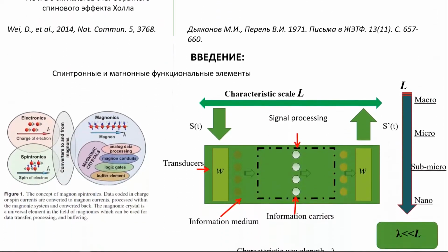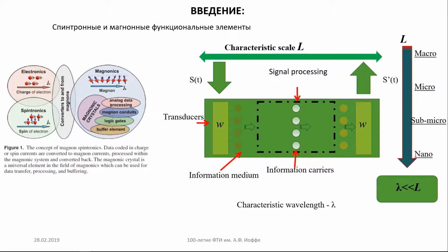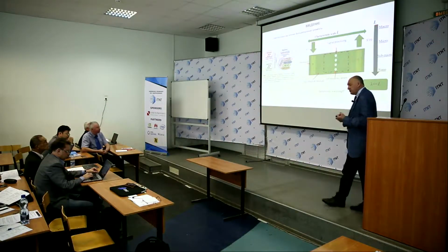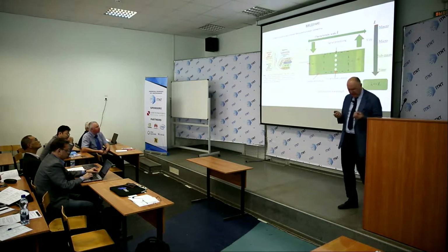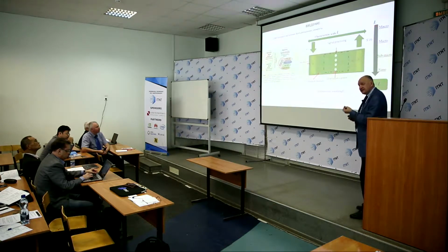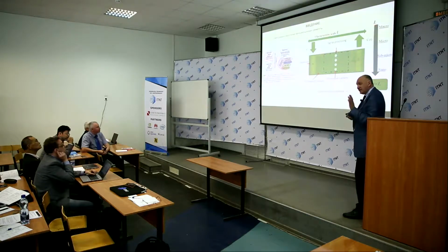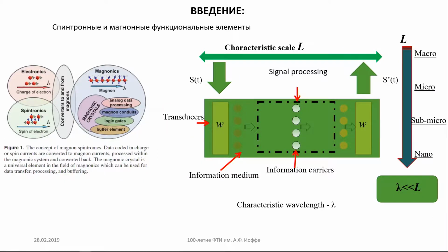So spintronic and magnonic functional elements have a very typical scheme in this picture. We have a magnetic material, which is the information medium, and carriers of information. In our case, information carriers are magnons or spin waves, so the change of magnetic moment of the magnetic material. And the information medium, basically, is a magnetic medium. The best medium for spin waves is the so-called yttrium iron garnet. This is a typical ferrimagnetic material. At frequencies of about gigahertz or even terahertz, its anisotropy is very small. There is only a small crystallographic anisotropy, which compared to the value of the magnetization itself of this material is very small. And you have some transducers which can create excitation of carriers, and you can create receivers of these carriers.